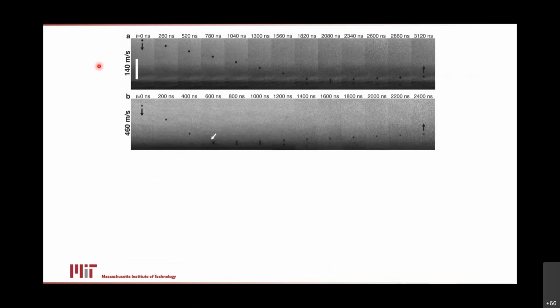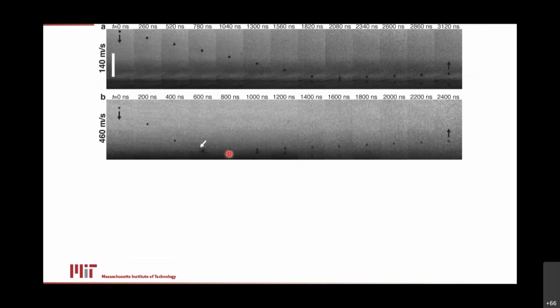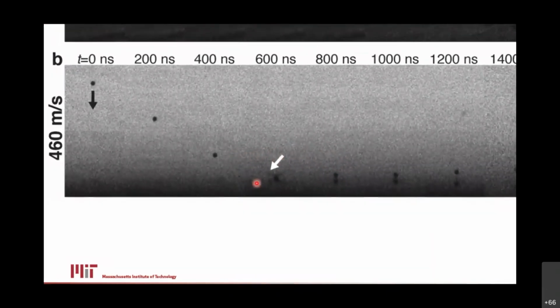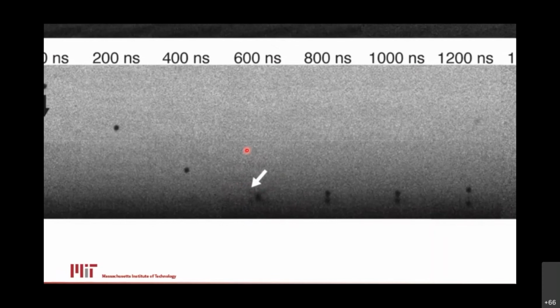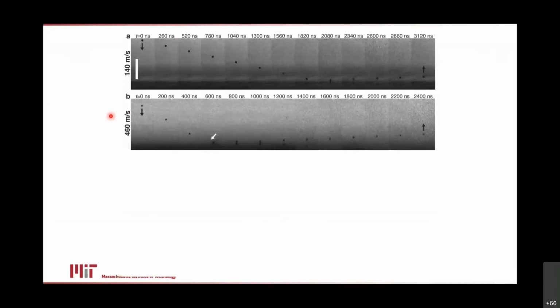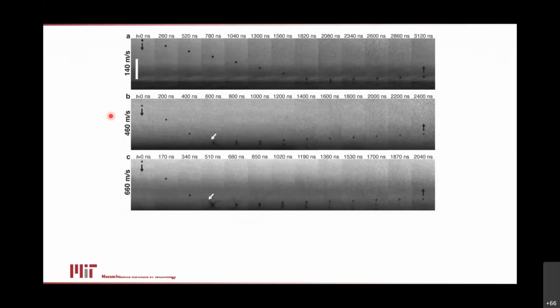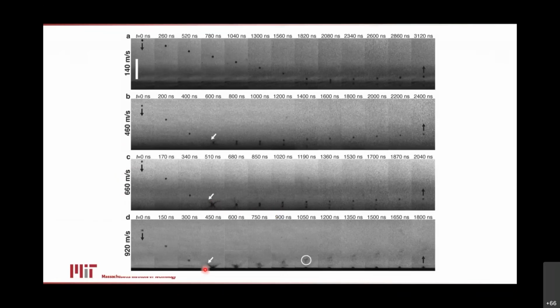So here's a particle that's bouncing. This is at a low velocity. When I go to a high velocity near the cusp, so this is near the breakdown regime now, this is 460 meters per second. And if you squint, you might just begin to see the hint of a splash here. In fact, I'm going to blow this up for you so that maybe now you don't need to squint, but you can see, indeed, there's a little splash in this video. So at 460, we start to see a softening and ejecta are produced. By the time we get to 660 meters per second, you don't need to squint anymore. It's a pretty convincing splash that lasts for dozens and dozens of nanoseconds. And at 920, it's not just a big splash that lasts a long time, but we actually see ejecta flying away for microseconds, like a huge, long falling action from the giant explosion of ejected matter.